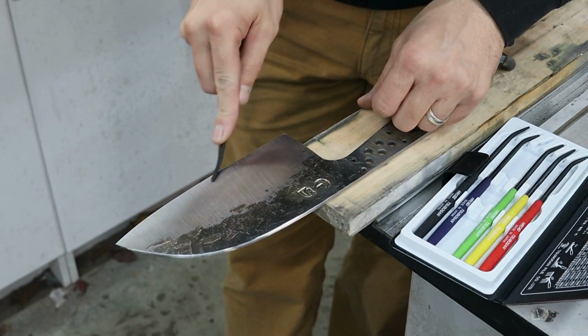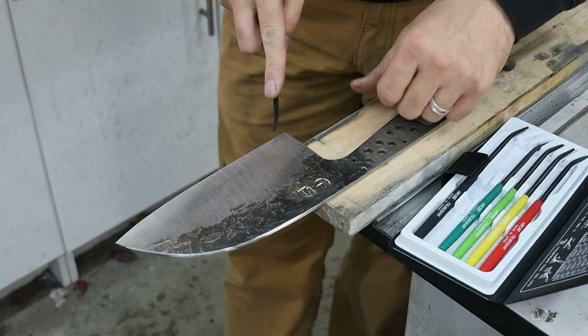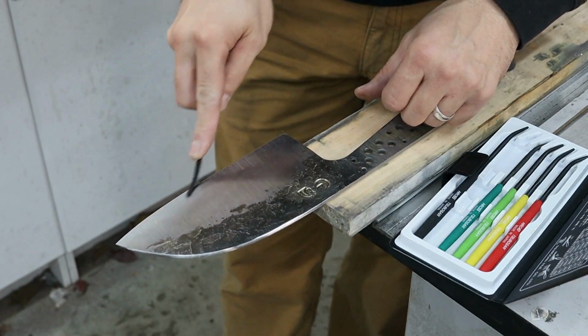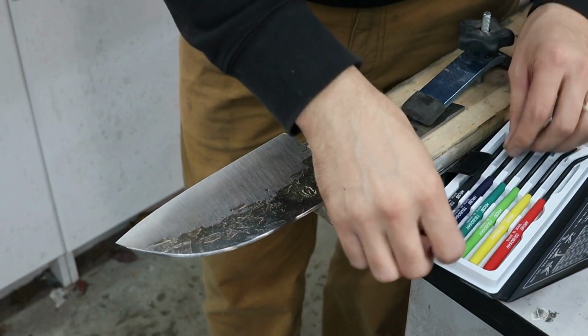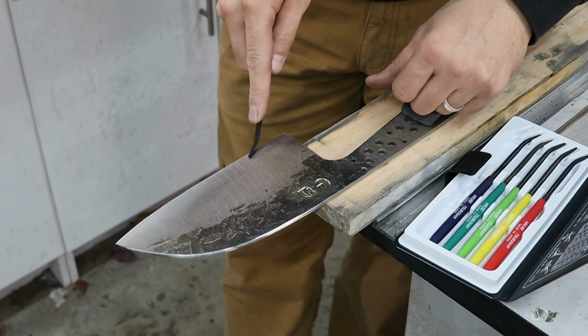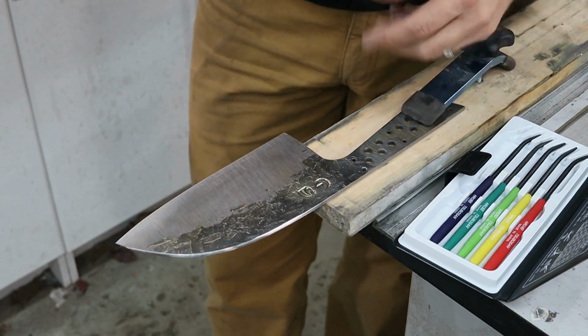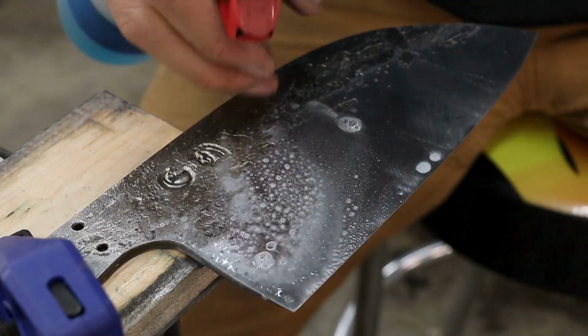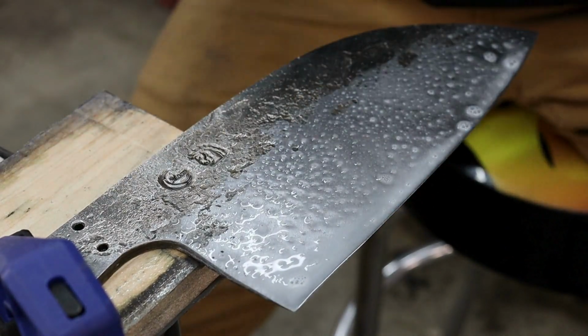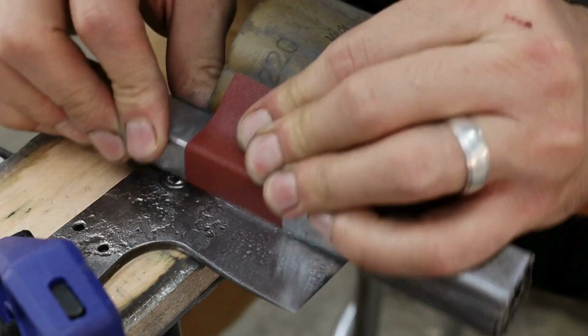I like to file test the edge for hardness after I've taken the bevels up to 120 grit on the belt grinder. This ensures that I'm through the decarb layer and gives me a really good idea of how hard the cutting edge actually is. This blade just barely skated a 60 Rockwell file, and the 65 Rockwell file easily dug in. I'd guess that the blade is probably around 60 to 61 Rockwell.